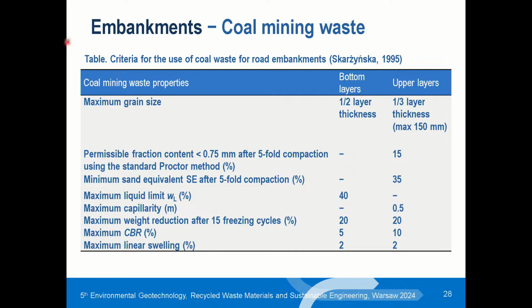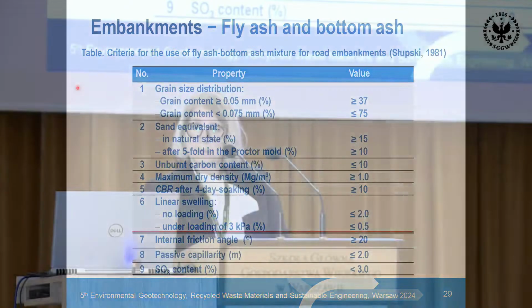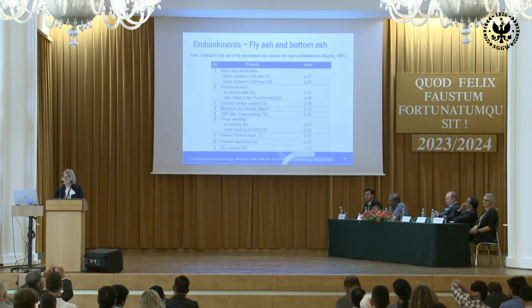most of the coal mining waste is well compacted, and it is a good material for the construction of road embankments, and the table presents the criteria for the use of coal waste for road embankments for the bottom and upper layers. Coal waste incorporated into embankments has a risk of spontaneous combustion when the content of the flammable parts exceeds 30%, and in highway embankments the organic content should be limited to 20%. The next is the criteria for using fly ash and bottom ash mix in the embankment.